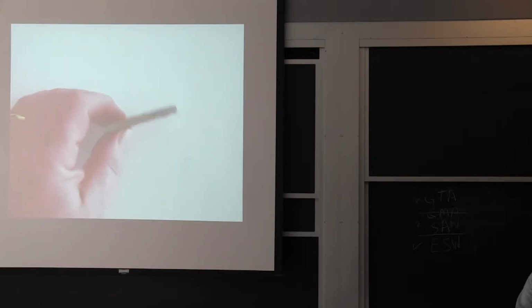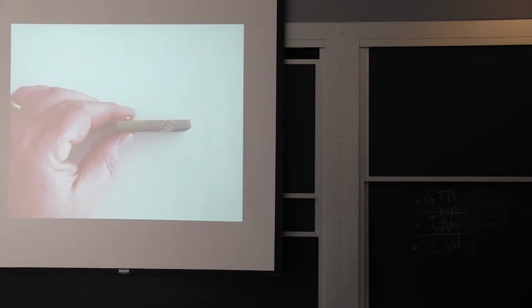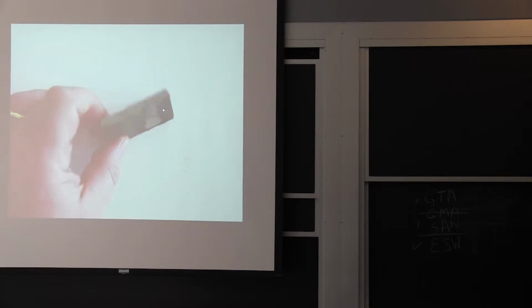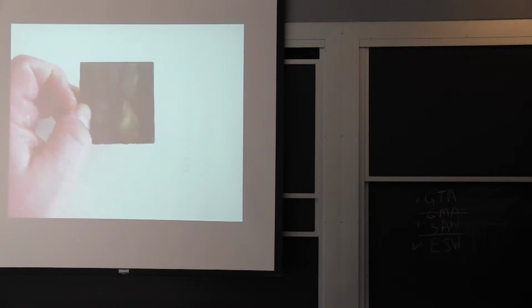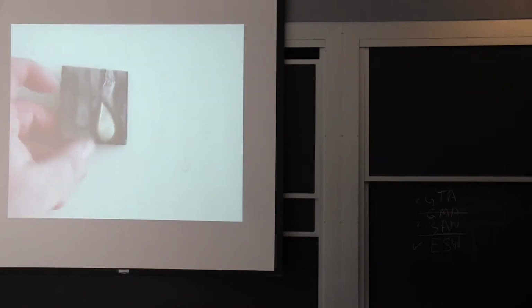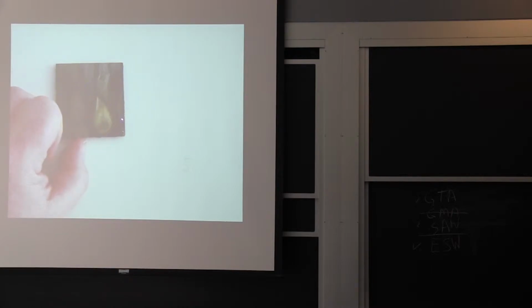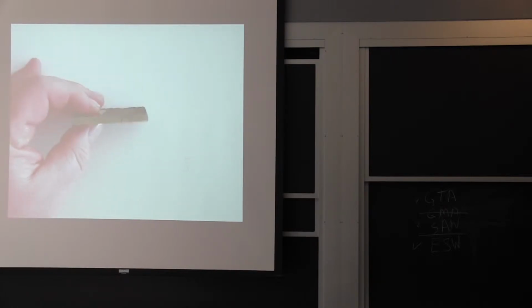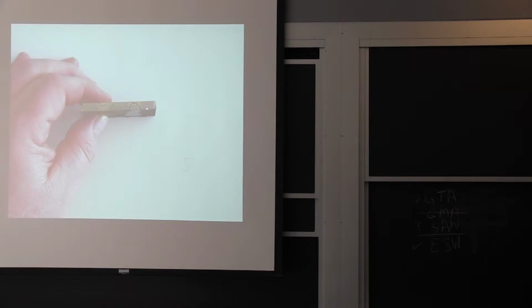And we did some of those first welds in this country. And here is end-on a smaller piece of titanium with gas tungsten arc. And I put a bead on this side and a bead on this side. This one was done with no flux, just argon shielding, which is the way you usually run gas tungsten arc. This one was done by putting a flux on the surface. You can actually still see a little bit of the flux. In fact, you can see on this one, if you look at the top, you can see where we started with no flux, and we had painted this little paint layer of calcium fluoride or strontium fluoride, may have a little sodium fluoride. And with the exact same welding parameters, you get this much penetration with no flux, and with flux, you would get 3 times the penetration.